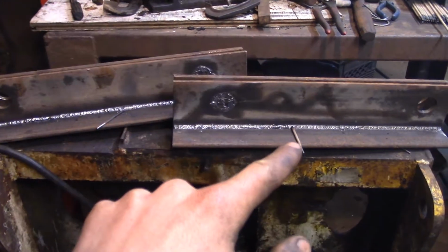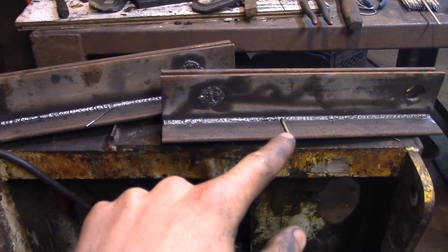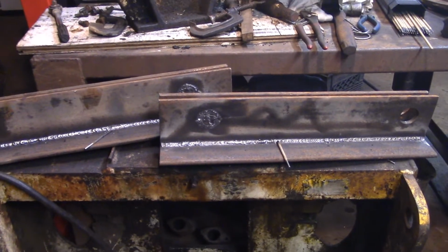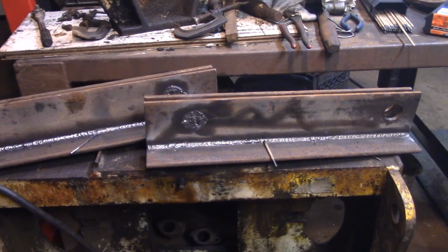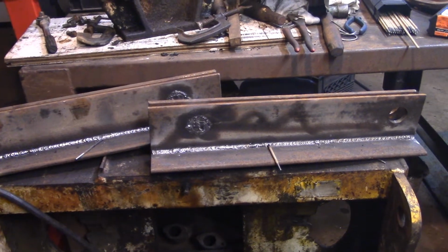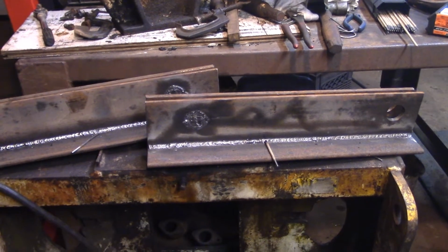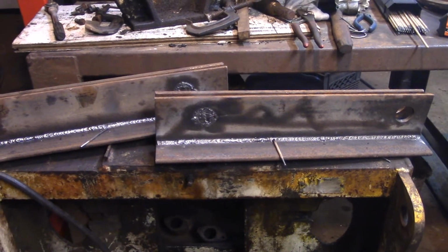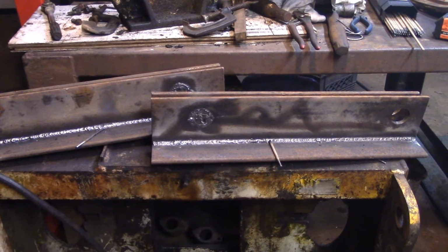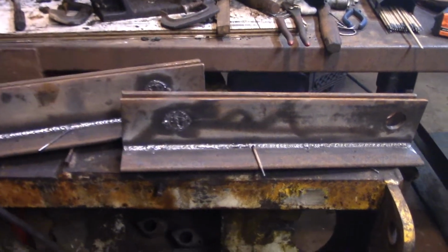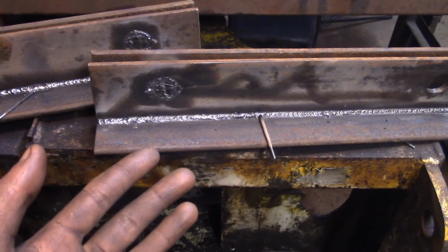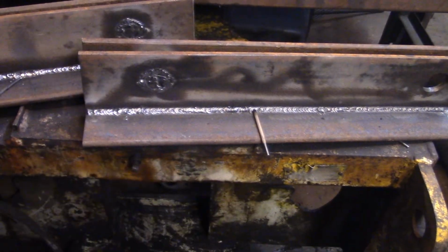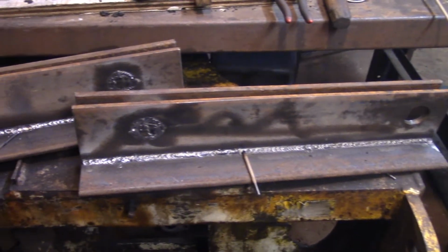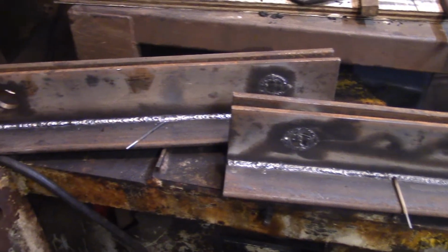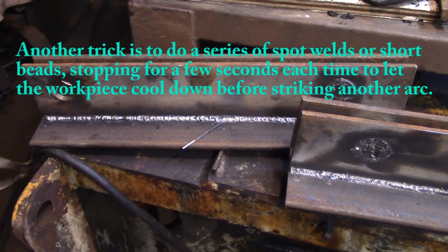And that's what I've done with this Lincoln rod. When I first got it, I did some welding with it, and I found that 95 amps was just right. I can go a little bit lower in the amperage if I need to, but it doesn't weld quite as well. If I was welding some thinner material, I might go for maybe 85 amps. I would do that. But 95 is just right. And if you need to weld thinner material, you should use a smaller welding rod, of course. But if you don't have it, if you're out in the field or whatever, you've got to use what you got, so you can lower the amperage a little bit and make it work. So that's one of my tips about heat.